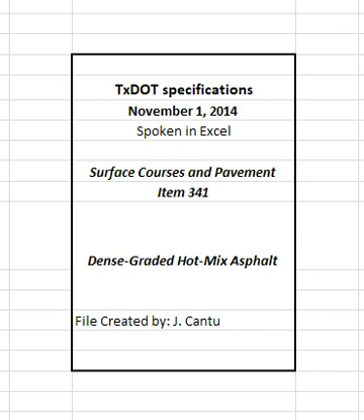Table 11. Operational tolerances. See table in specifications. 1. The contractor may request referee testing only when values exceed these tolerances. 2. When within these tolerances, mixture production gradations may fall outside the master grading limits, however, the percent passing the number 200 will be considered out of tolerance when outside the master grading limits. 3. Only applies to mixture produced for Lot 1 and higher. 4. Test and verify that Table 8 requirements are met.